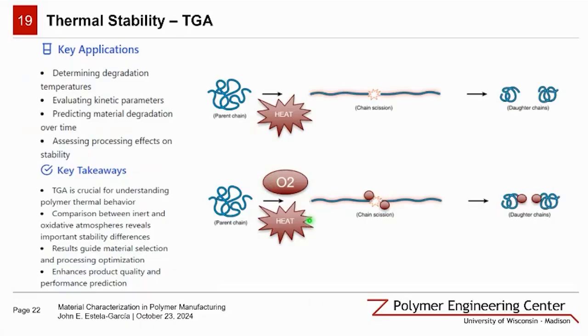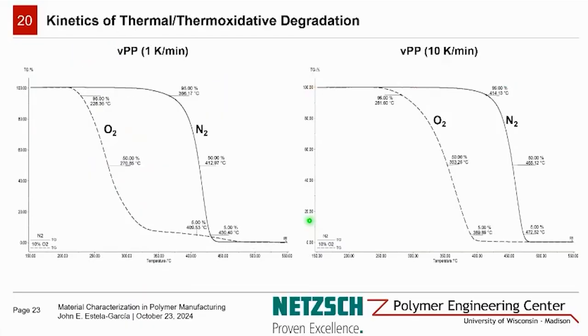And this particular knowledge is useful when you're trying to compare the thermal history of recycled materials, where the history that the recycled material has gone through impacts the material properties. So on this slide, we can appreciate the comparison between the thermograms of polypropylene subjected to an inert environment and an oxidative environment at two different heating rates. It's important to note that for the oxygenated environment, we utilize 10% oxygen. This is taking the assumption that oxygen has poor permeability throughout the polymer melt.